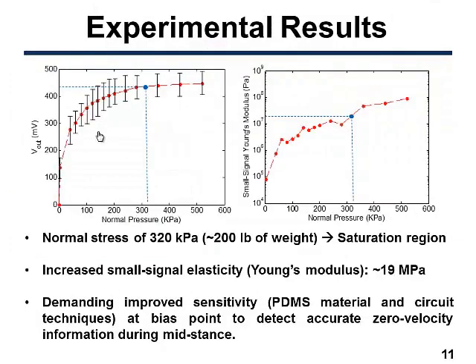This slide shows the characterization of a particular sensor node. The normal stress of about 320 kilopascal is estimated based on 200 lb of weight on a single foot. As you can see, with the pressure increase at about our bias point, our sensor starts to go close to the saturation region. This leads to an increased small signal Young's modulus, or you can call it the slope here, which is also calculated and plotted on the right plot.